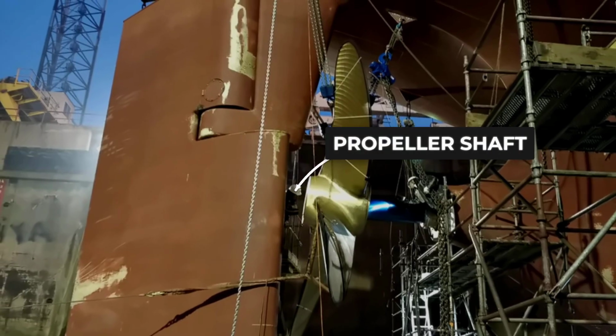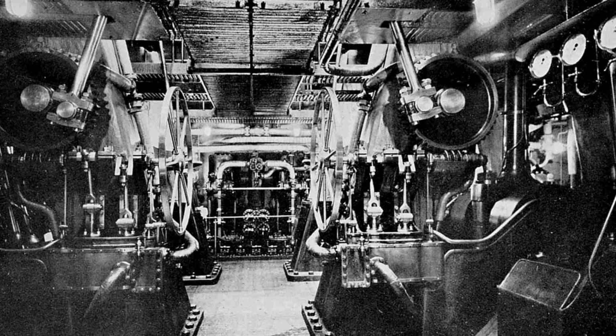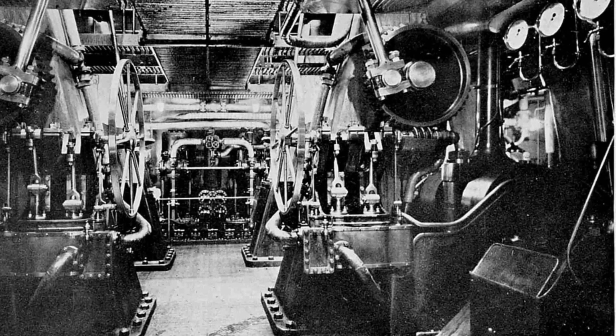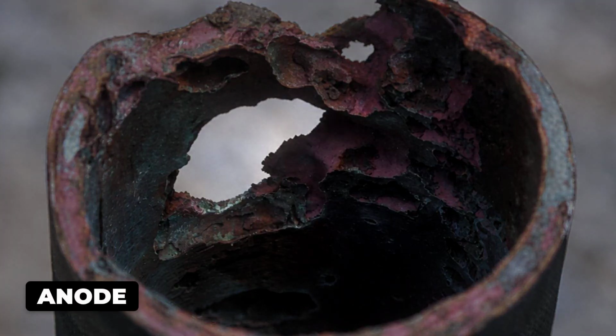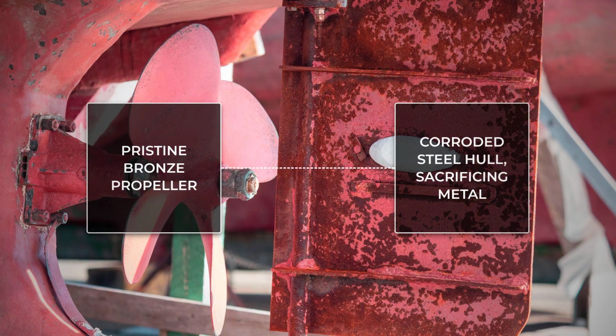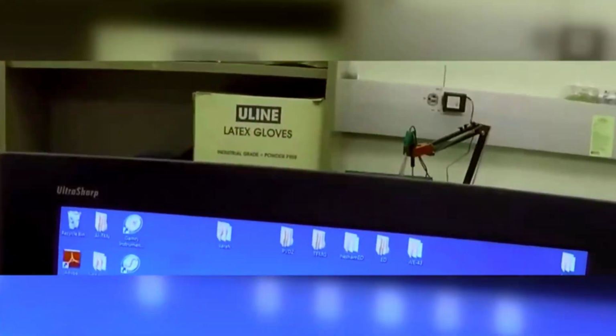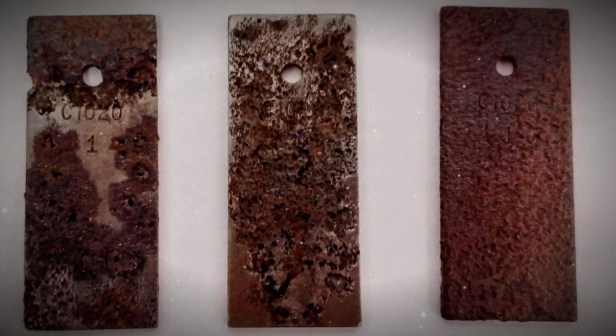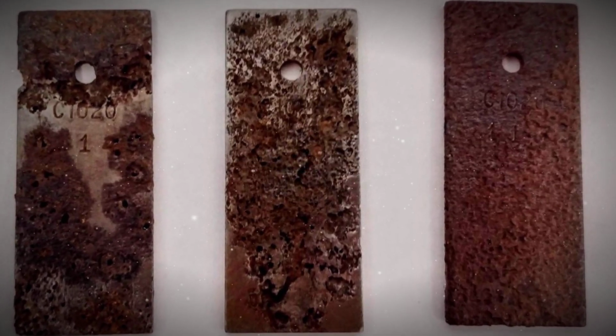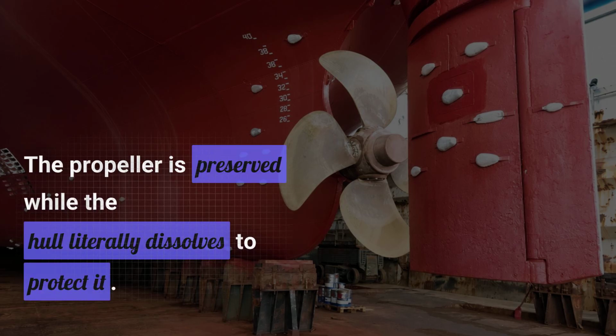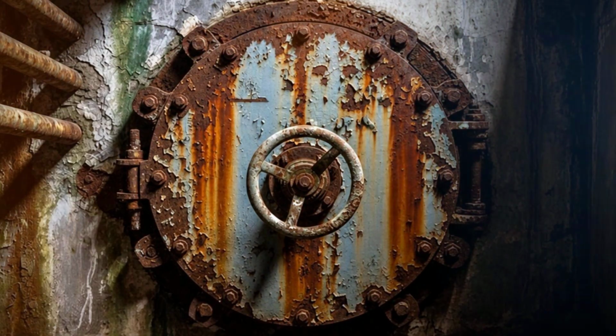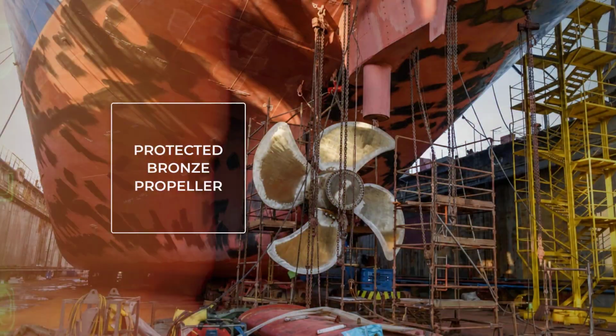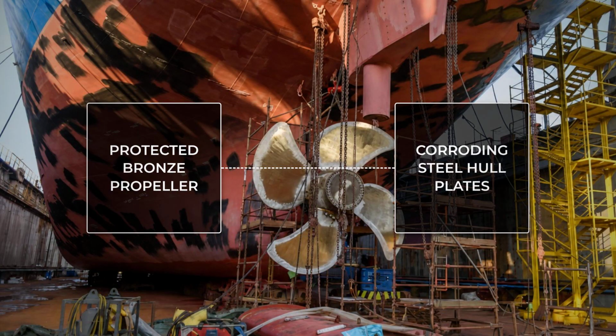By coupling the noble bronze propeller directly to the steel hull through the propulsion shaft, engineers had completed a massive electrical circuit. In this wet environment, the steel hull acts as the anode, sacrificing its own metal to keep the cathodic bronze propeller pristine. Modern electrochemical studies confirm that even modest steel-to-bronze surface area ratios can accelerate the local corrosion rate of adjacent steel several-fold. The propeller survives because the surrounding ship is literally dissolving to save it. It is the engineering equivalent of keeping a lock pristine by letting the vault door rust away. Protecting the drive gear comes at the direct expense of the hull.